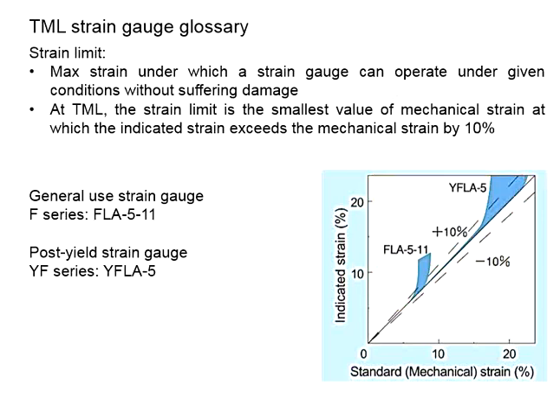Knowing their limits leads to the selection of a suitable strain gauge for your testing. Now, this FLA 5-11, which is known as the F-series strain gauge, is applicable for general users. Taking a steel bar as an example, a typical carbon steel yields at somewhere around 10% elongation. It could be slightly less than 10%. If you are measuring the elastic response of carbon steel, then you can use this. But if you want to measure the response of the carbon steel after yielding, this one will not be applicable. Even though you use this, there may be a value, but the value will not be accurate. The variations can go beyond plus minus 10%.